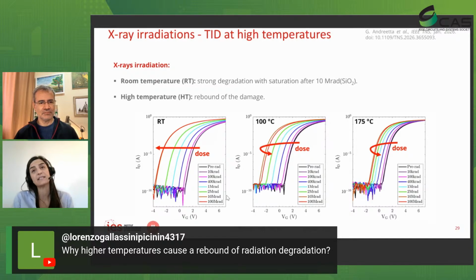Yeah, something else I didn't mention also is we also stress the device, applying a bias without having irradiation, just to assess whether there was a degradation of the threshold voltage just due to the electric stress, but it's negligible compared to what we observe with the radiation. But yeah, I would say that there is some dynamic annealing already happening during the irradiation here.